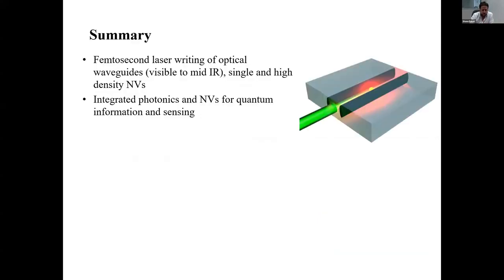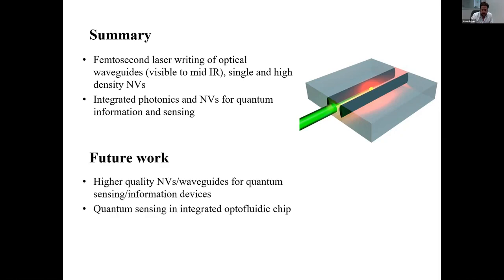So in summary, I hope I've convinced you that femtosecond laser writing is a very versatile tool. You can form not only optical waveguides. I demonstrated visible waveguides, but we've actually demonstrated in our group waveguides that work in the near infrared, up into the mid infrared, and possibly up to terahertz. We've demonstrated we can form both single NVs, which are useful for quantum information, and high density NVs, more useful for quantum sensing. And so the idea is working towards integrated photonics for NVs for both quantum information and sensing.